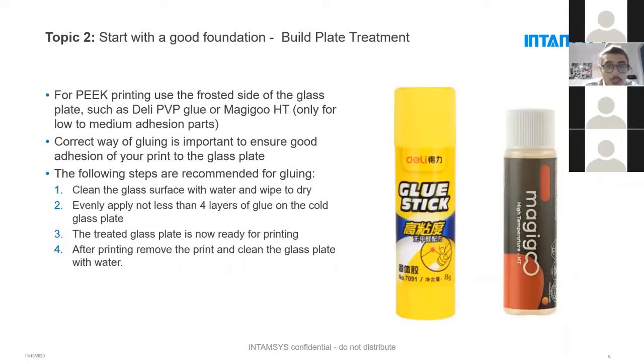Topic number 2. Start with a good foundation, build plate treatment. To have success with printing, especially with FFF technology, it's very important to have a good adhesion from your part to the build plate. So this is why we have a strict guide with a strict glue to say, okay, if you follow this glue, you have a good adhesion to avoid any failure. Due to expensive material, we do recommend to exactly follow this guide to not lose any gram of material.